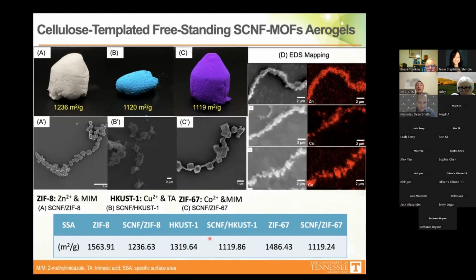As I said, the metal organic framework is special because it has a really high pore structure, which means it has a high surface area. So we determined the surface area, and this is the MOF without nanocellulose, and this is the nanocellulose hybridized one, for all the three. It turned out that the hybridized nanocellulose and MOF had a really high specific surface area, more than 1,000 square meters per gram, which is about a couple hundred lower than their counterpart. But it's still really high.